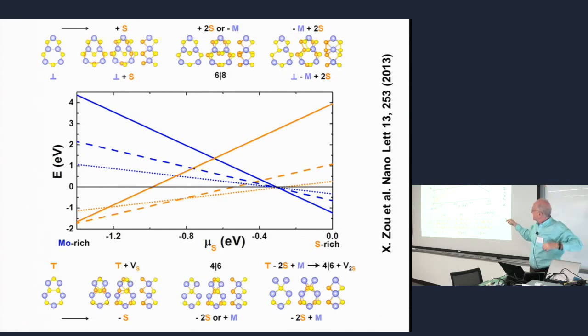They have different chemistry, which means the energy of formation of this defect, again, is not one number. They are lines depending on chemical preference, chemical composition, and they depend on chemical potential. In this case, maybe sulfur, because gas phase sulfur usually is present. So you have these lines, and depending where you are, you can prefer this one or this one or that one. So that's very important because then it allows you to figure out what's going on in the zoo of defects. It may be different material, but the concept is still the same.